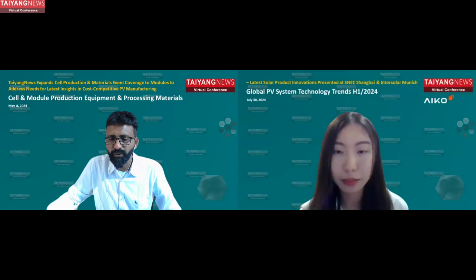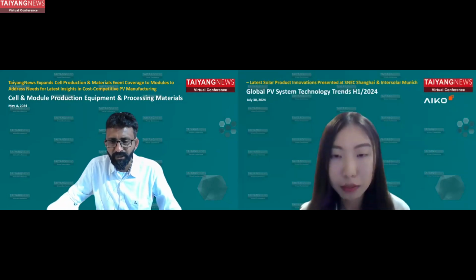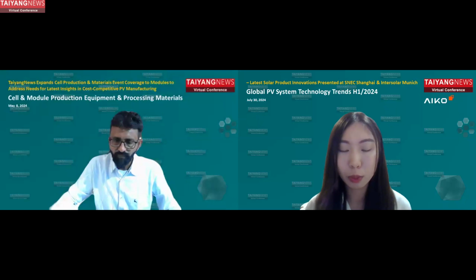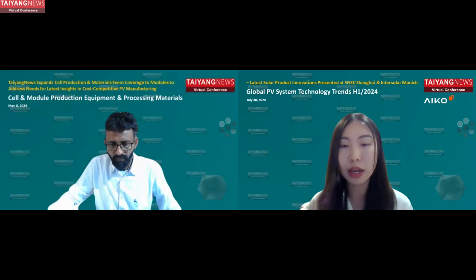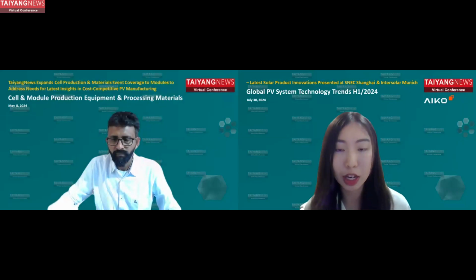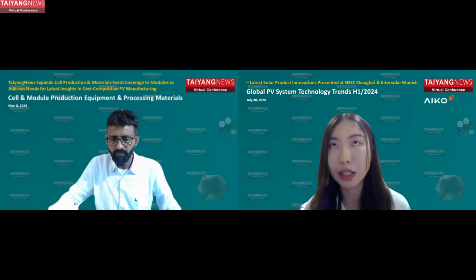Okay, one more question. You mentioned you are also entering the bifacial segment with your technology. Can you say what the bifaciality is? For the Infinite product? Yes. Actually, that one is not determined yet, because we put the interconnection bus bar at the backside, which means we lose some area on the backside for the bifacial rate. But as I mentioned before, this product is not in mass production right now. We are still finding ways to improve this. Right now in the lab it is around 60% bifaciality, but I think we can increase this further.